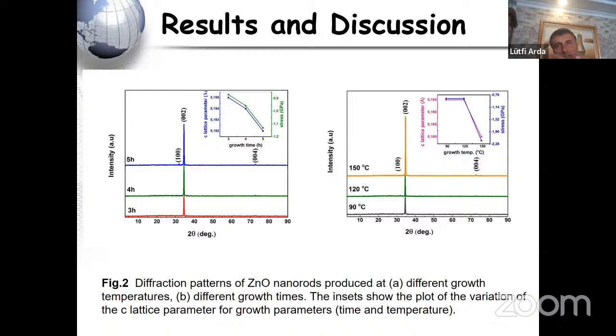It was detected for all zinc oxide nanorods, confirming the preferential orientation of the grains along the C-axis, which is orthogonal to the substrate. Also, when we look at these figures, the intensity of the 002 peaks increases with an increase in growth time. Growth temperature is the left side, and the growth time is the B part. This can be credited to a better crystallinity of the film.